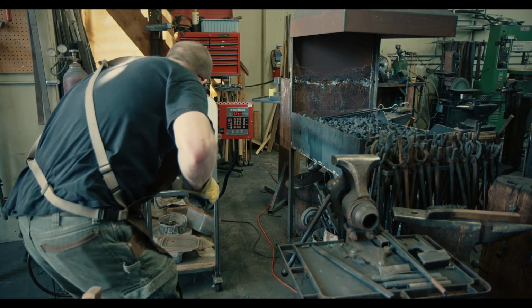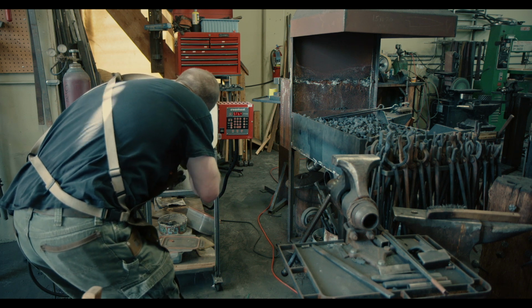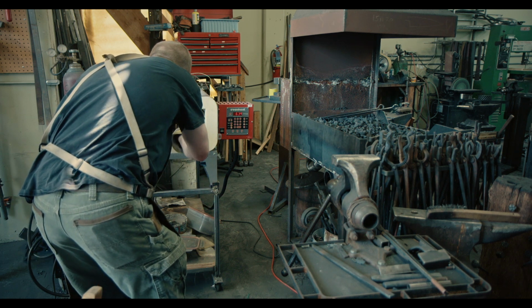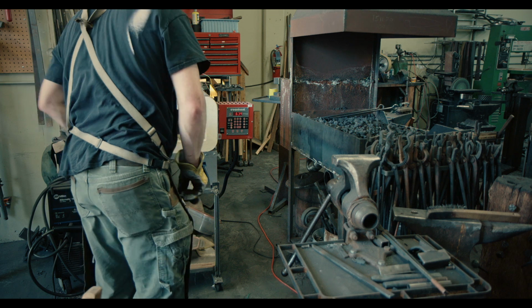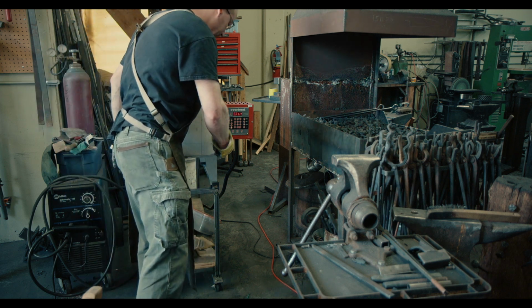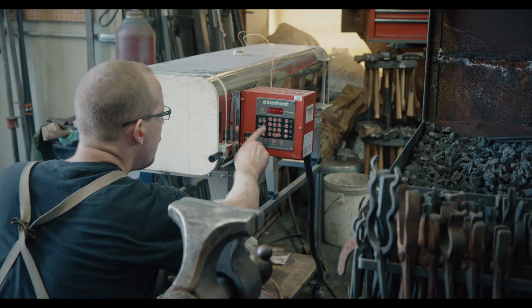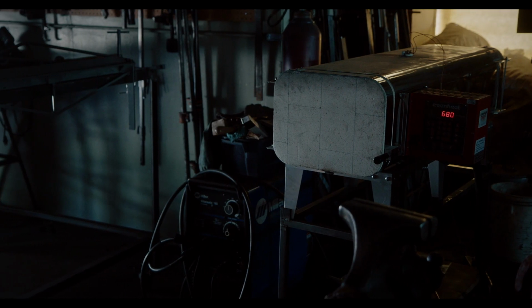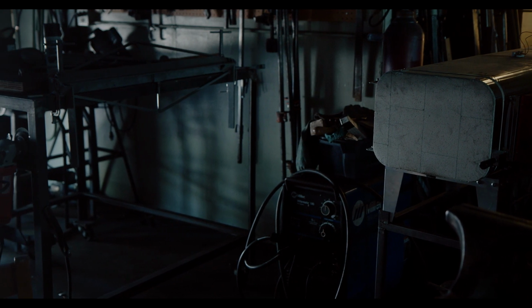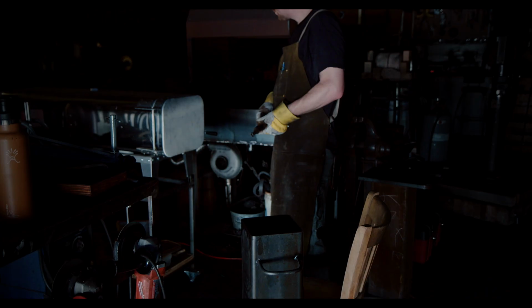The moment of truth has arrived. The electric oven will heat the sword up to 1500 Fahrenheit, that's 815 Celsius, and then I will quickly move the sword into the room temperature quenching oil. At this point, I've invested somewhere between 40 to 50 hours into making the sword, and if I'm unlucky, may waste that time in a matter of seconds.